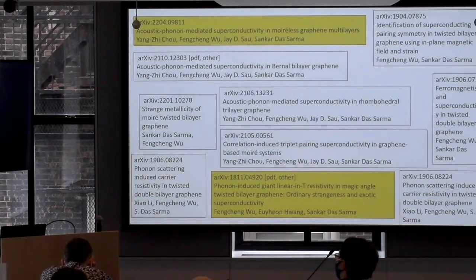But I have this feeling, having done a lot of electron-phonon calculations, that not everything can be explained by electron-phonon. Now, Steve Kivelson tells me that he also thinks electron-phonon may play a role. The real mystery is that you have many, many phonons, like 5 different atoms in the unit cell. Why is the slope always the same? You think there should be little kinks. He thinks some kind of large N theory can resolve that, and I have not thought deeply about it. So all I'm saying is a precise statement: electron-phonon interaction has not been ruled out decisively there for resistivity.